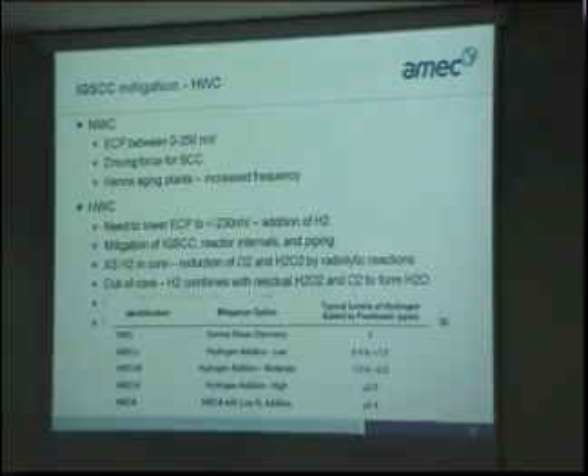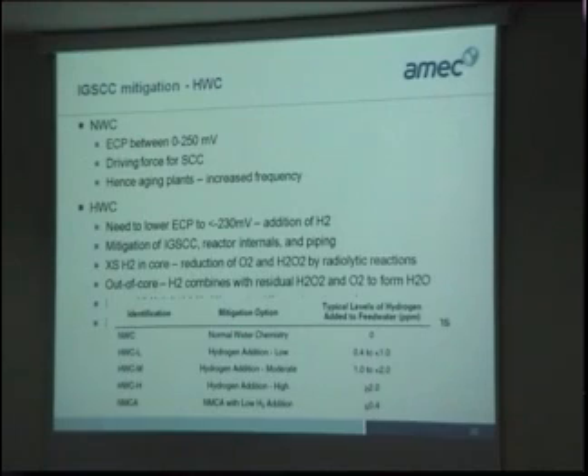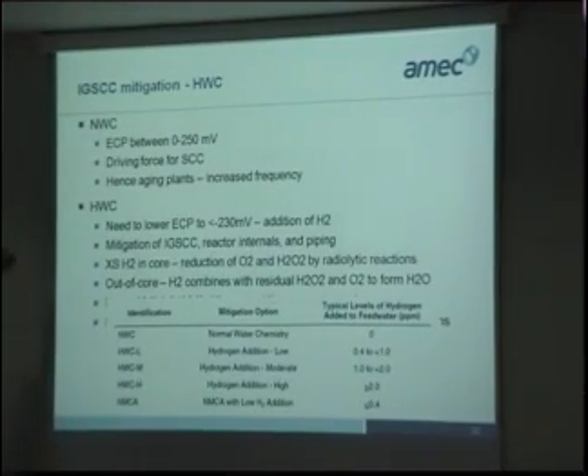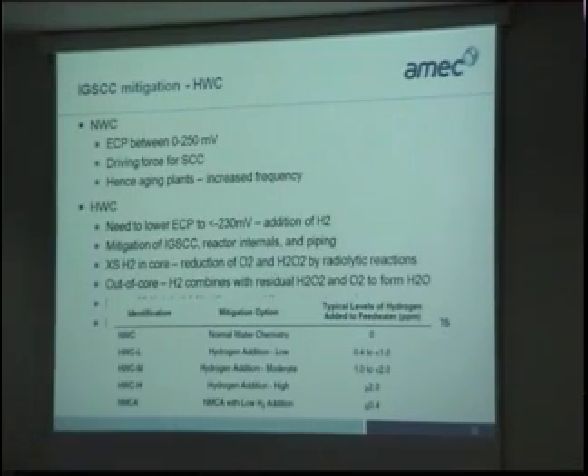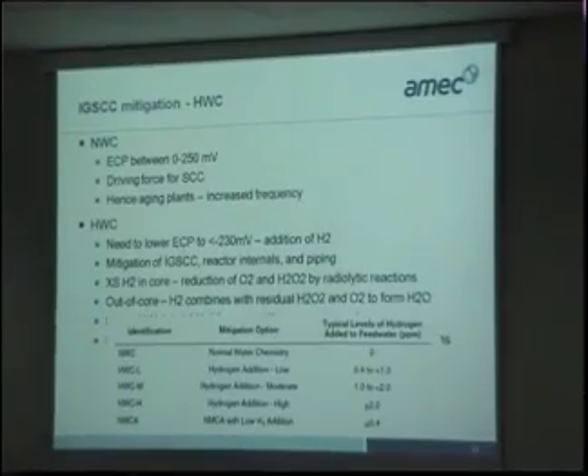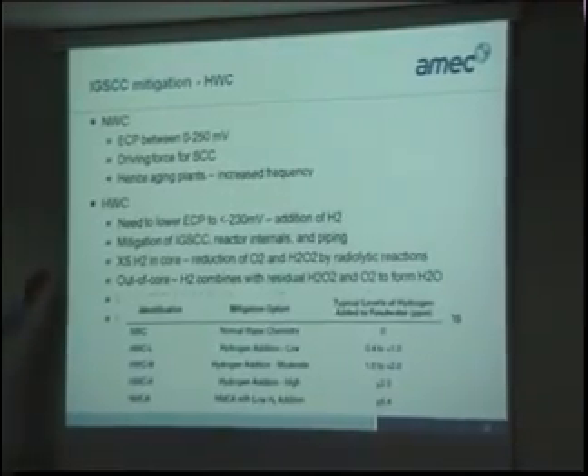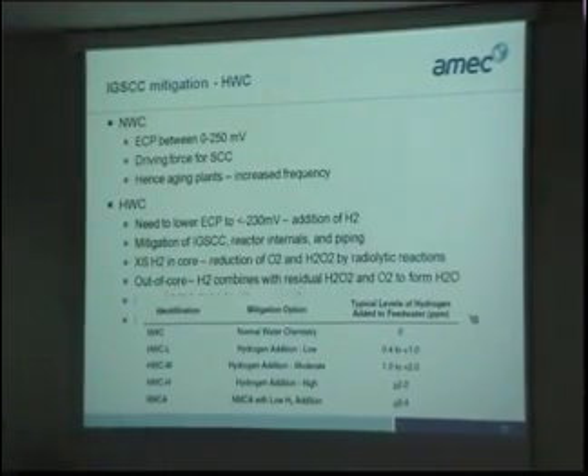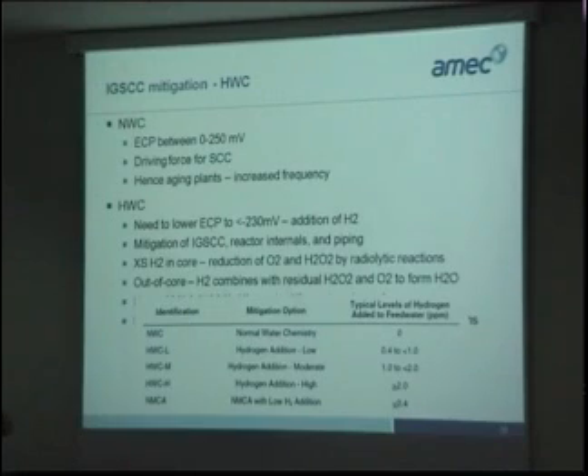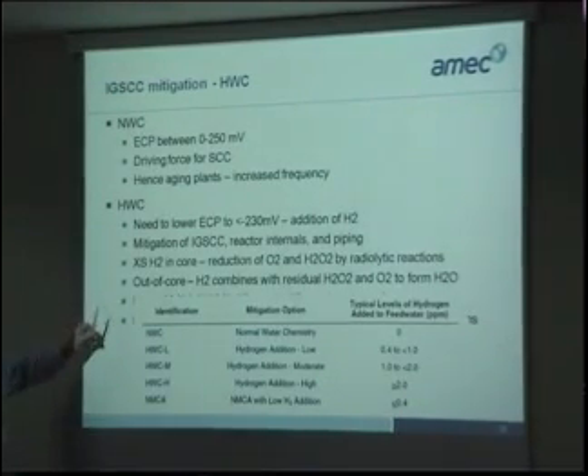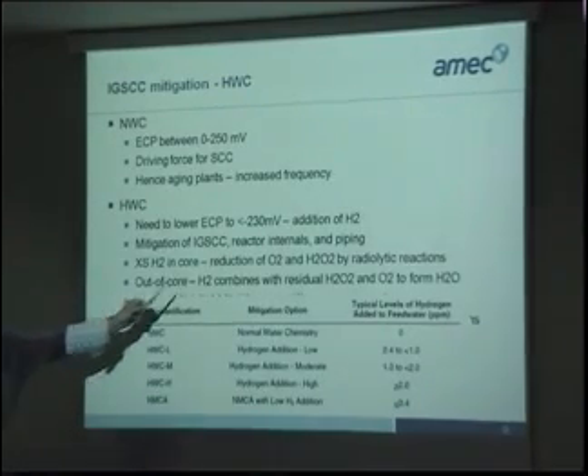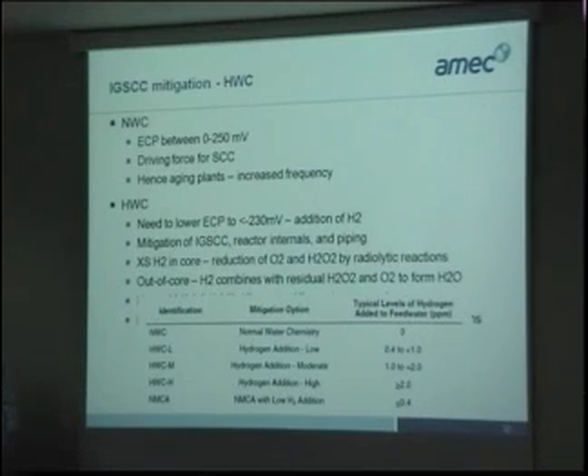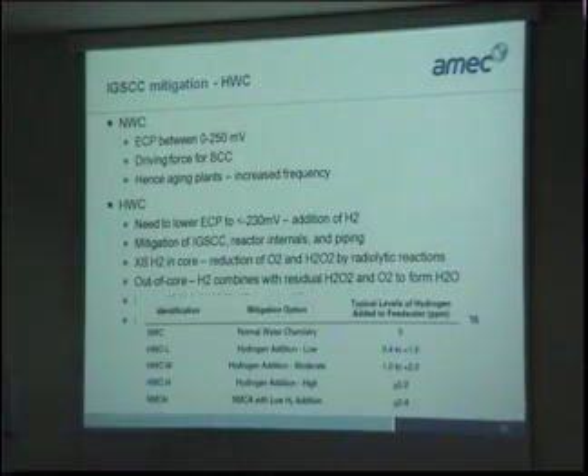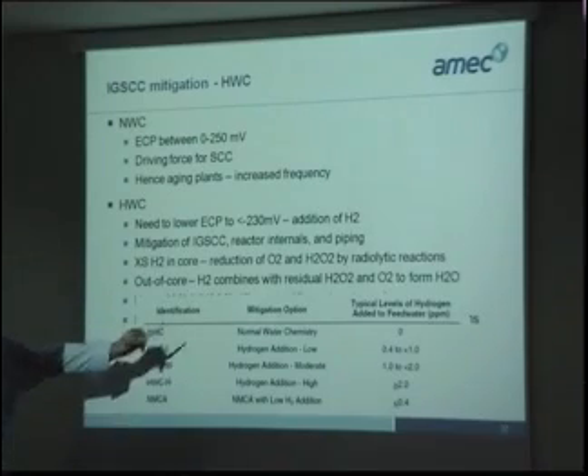So if we look at comparison with, say, normal water chemistry and hydrogen water chemistry, the ECP here was quite high, and there's the driving force for stress corrosion cracking. So invariably for aging plants, we see an increased frequency of SCC. With here, we're down to minus 230 millivolts, which is the sort of the optimum range with the addition of hydrogen. And we've seen mitigation of stress corrosion cracking, reduction of oxidizing species. And it's interesting, although we talk about hydrogen water chemistry, we can have various types of hydrogen water chemistry, low, moderate and high. And various plants have adopted all of these regimes. You can see going from 0.4 up to 2 parts per million.